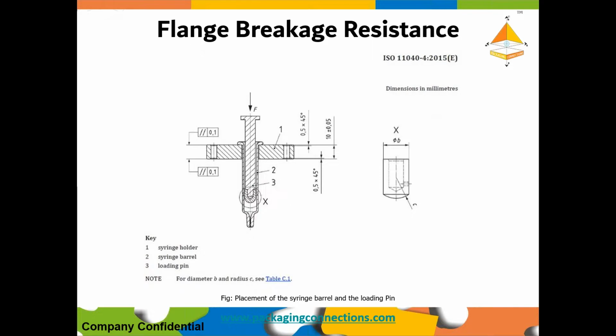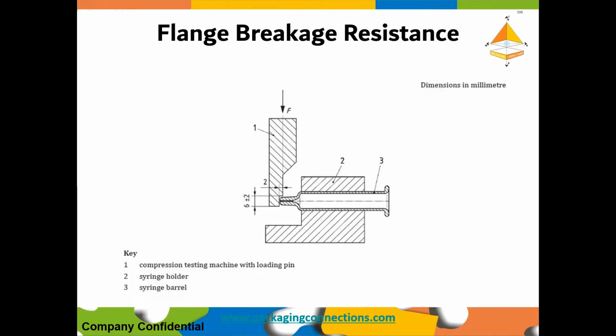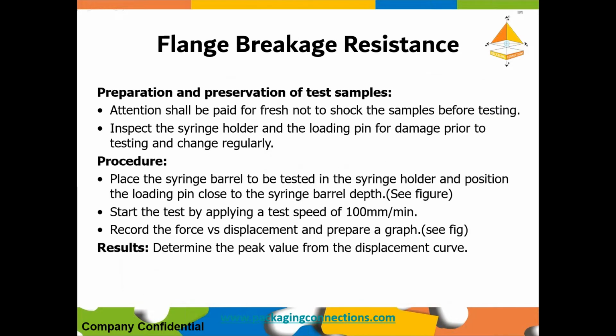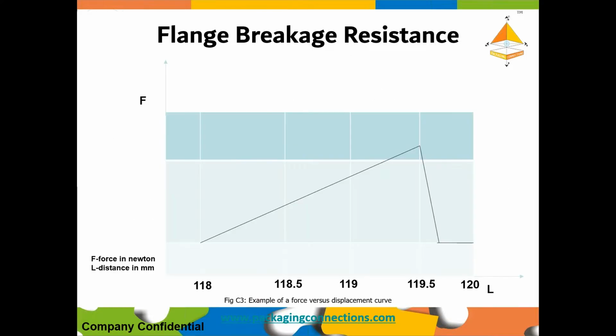Flange breakage test. This is another one, when we want to do the compression of it. When we are preparing the samples, it is very, very important that the samples are handled very delicately, because if the samples go through a shock before testing, we will not get the right results. And flange breakage resistance is tested as a force in Newton and distance in mm. So you could see when it breaks.